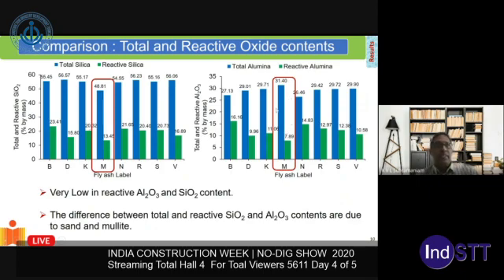So this is a lesson for us, where we realize that the fly ash, whether it is the production process, the boilers that are used, the temperature of processing, or the collection, there is fundamentally the fly ash we're using is of a very low reactive content.